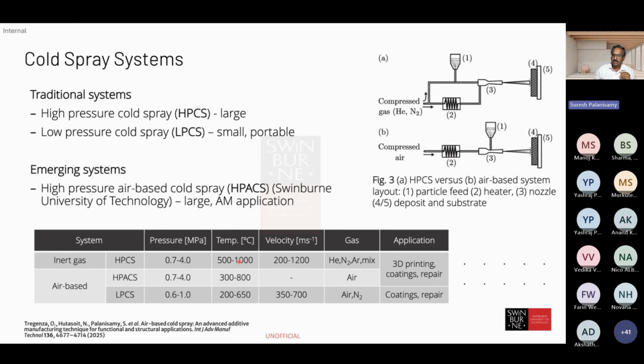The velocity ranges also differ depending on the gases you use. For example, if you are using inert gases with high pressure, which is obviously 7 bars to 40 bars range or more than that, and the temperature can be high, high velocity can be achieved. In this case, mostly 3D printing, coating and repair applications can use this. Most of the work I'll be talking about will be in this particular area because that's the equipment we have, a high pressure air-based cold spray system. That's the system we have, and that's what most of my talk will relate to.